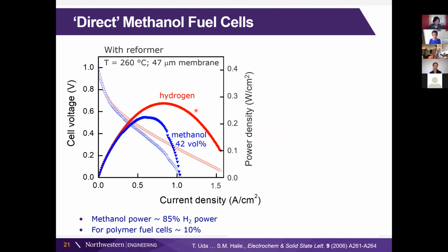So how it performs then is when we have hydrogen here as our fuel, and compare that to delivering methanol with a lot of water as well. So 42 volume percent methanol and then balanced steam, because we need that to do that reforming reaction. We can see that we're getting about 85% peak power compared to hydrogen, which is a really good value for polymer systems. You might be on the order of around 10%.